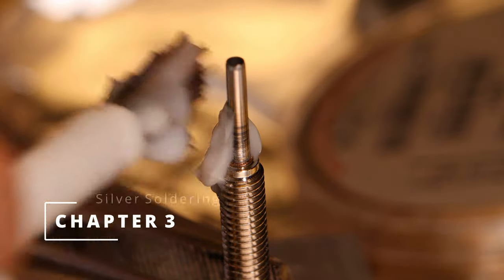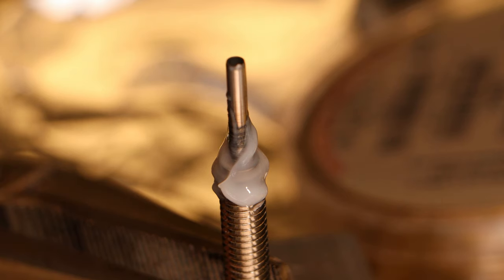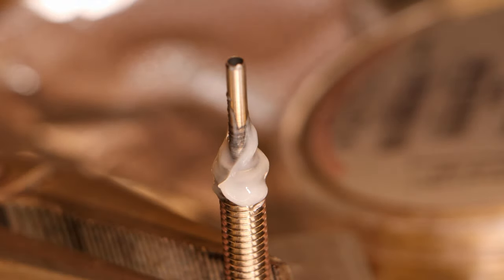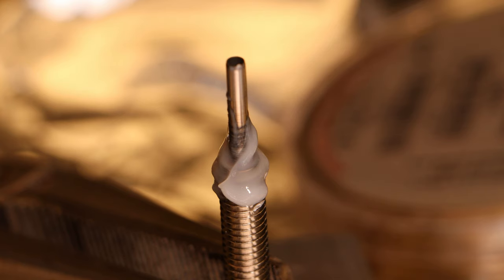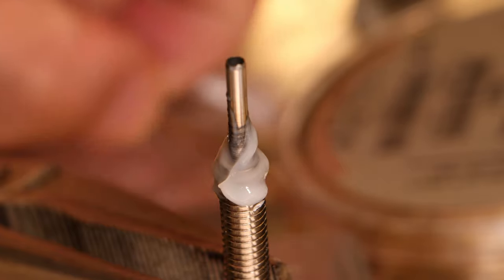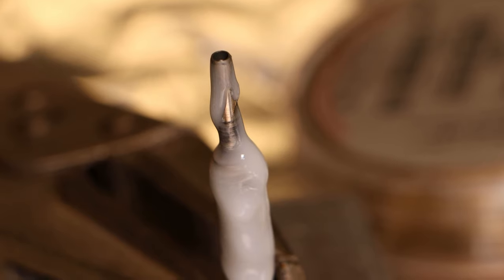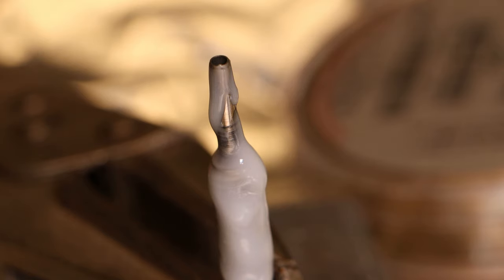First, I'm going to apply some flux. It's a generous amount there. And I'm going to want to be careful to not put too much heat into the stainless steel. The stainless steel has a higher melting temperature so it can handle more heat, but it's also a lot thinner, so it'll heat up faster and there's a real chance I might melt through it. So I'm going to concentrate most of the heat down on the bottom. And I'm just covering everything generously in this brazing flux because I don't want things to start oxidizing while I'm working.